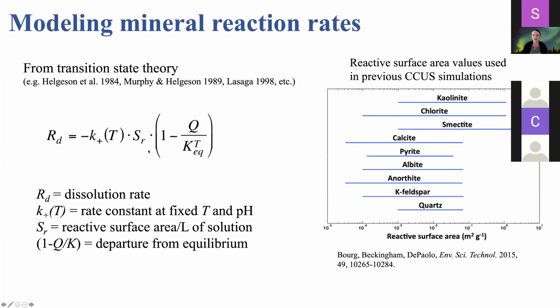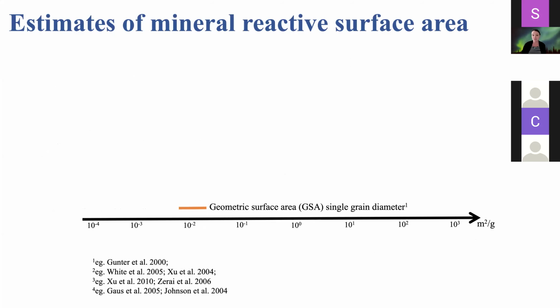In fact, if you gather reactive surface area values that were used in prior simulations of CO2 sequestration, and I've plotted them here, you can see that we have really large variations in the surface area values that we're using. And since this is directly proportional to the rates in our reactive transport simulations, you can see this is going to be a challenge. So why are the values so large? Well, let's talk a little bit more about how we're getting these values.